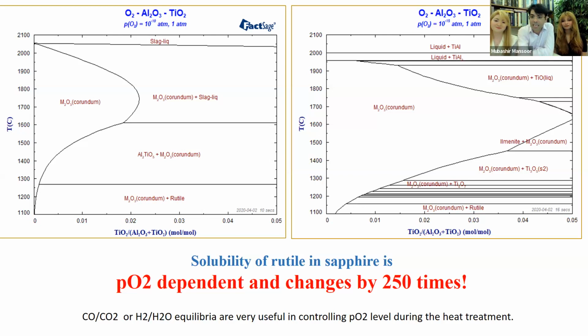And what's even more, it reduces the temperature of maximum solubility to about 1630 degrees Celsius, which is highly desirable because most furnaces can go up to these temperatures very easily. The process becomes much easier in terms of practicality. And we were talking with Ted Themelis about these observations, the calculations that we have had. And he mentioned something quite phenomenal. He said, well, you mentioned 1630, and I call that in my book the magic temperature, because I have witnessed this from an experimental side, that if you reduce the oxygen and you go to 1630, you get the best results. Well, no doubt. We get these out of the calculations as well.